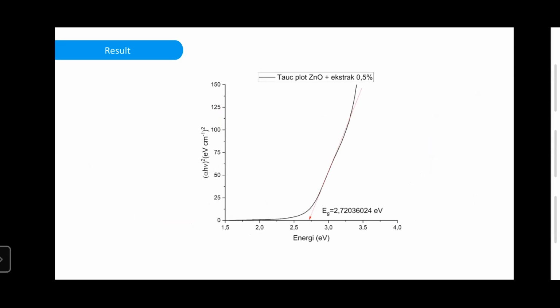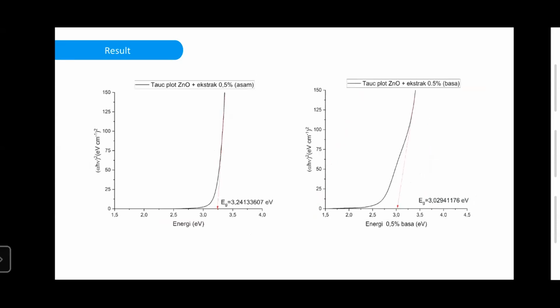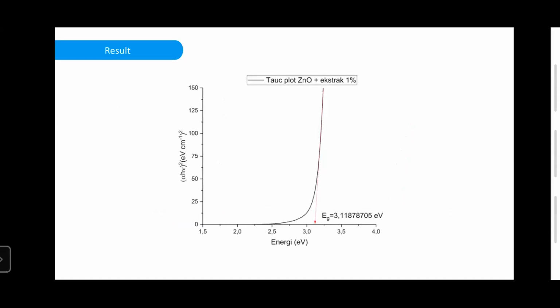And then this is for the sample that uses 0.5% extract. It has a lower energy gap than before. It is just 2.72 electron volt. And then when I add some acid solution, the energy gap is increased to 3.24. And when I add some basic solution, the energy gap is 3.02 electron volt.